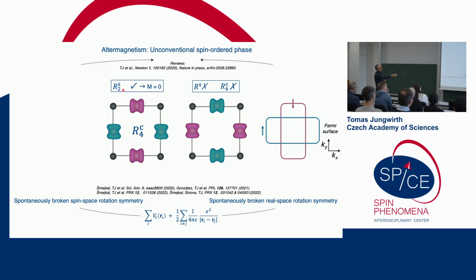But when I now combine it with the twofold spin space rotation, that means I flip the spins or I change the colors, this is what happens: I'm back to the original state. So individually, the two symmetries are broken, but a combination of these two operations is a symmetry of an altermagnetic system. And that's very important for altermagnets because this symmetry protects zero net magnetization, zero total magnetization in the system. Because my opposite spin densities in the crystal are connected with a symmetry. And that dictates that they fully compensate each other.